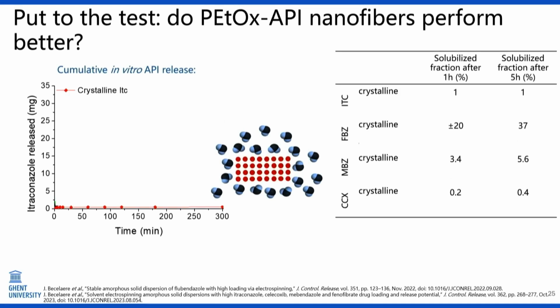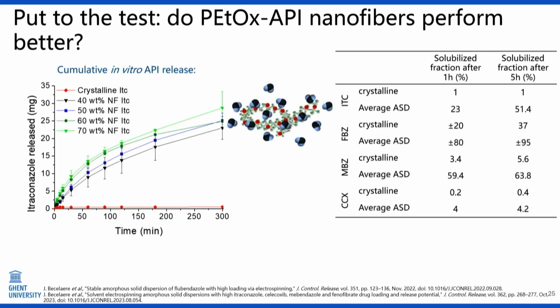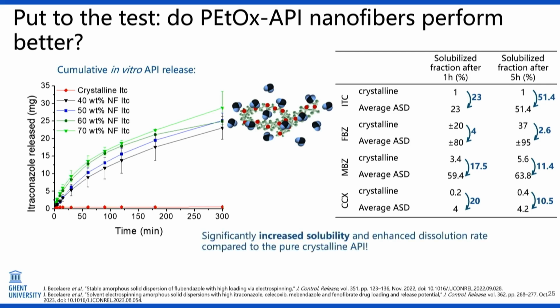We first tested this in vitro, and this is the solubility of the crystalline drug as being produced, which is, as you can see, very low. But if we use amorphous solid dispersions, we've increased solubility, depending on the type of API, up to a factor of 50 times. Which was a really interesting result.